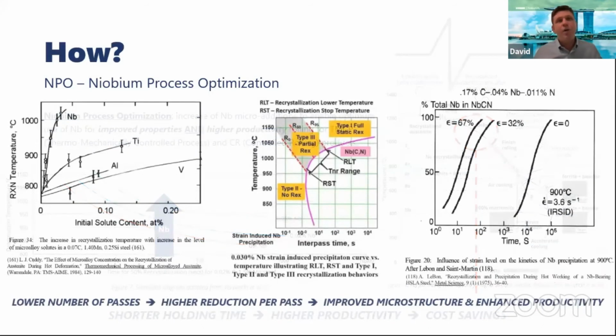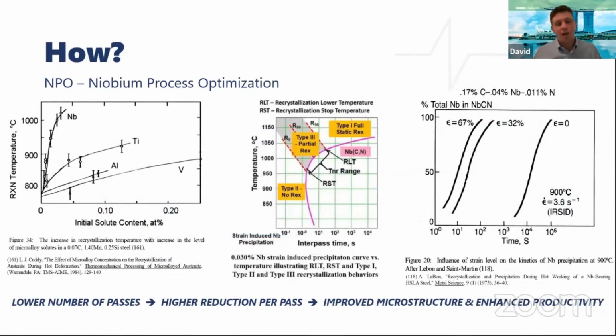Niobium is also known to have a stronger effect when higher reductions per pass are done. In other words, we can reduce the total amount of passes and increase the reduction per pass, of course, respecting the limitations of the machine, of the equipment. But that could also lead to more homogeneous microstructures and at the same time, a more productive rolling process.